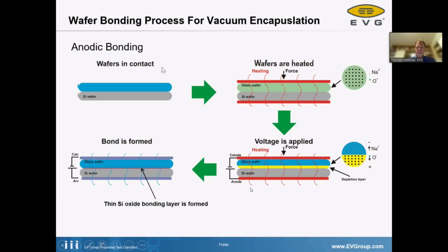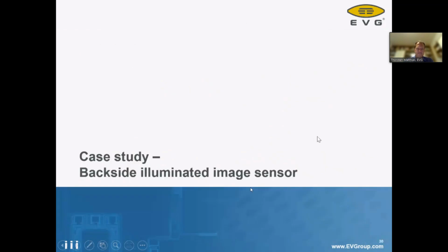So anodic bonding is being used for very harsh devices like pressure sensors, higher pressure sensors, all this kind. But if you need a super strong interface, then anodic bonding is definitely one of the good candidates, because we have this migration of the oxide ions into the interface, and I create an oxide layer in the interface, I grow a really strong mechanical contact between my two wafers.